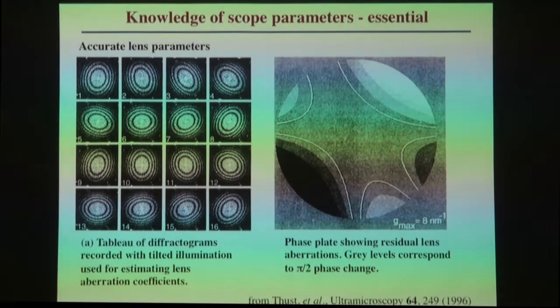What else is essential? You need to know the microscope parameters. This is from the work of Thust way back when, which I think was very important historically. If you tilt the illumination in different directions and record an image, and then get the diffractogram, you get a whole tableau of diffractograms like this. If you know how much you've tilted in one direction or the other, and then you go backwards, you can work out what is called the phase plate. This phase plate tells you about the residual aberrations. And so on this scale of Thust, the gray levels here correspond to a pi over 2 phase change. I'll come back to talk about the importance of pi over 2 or pi over 6 in a little while.